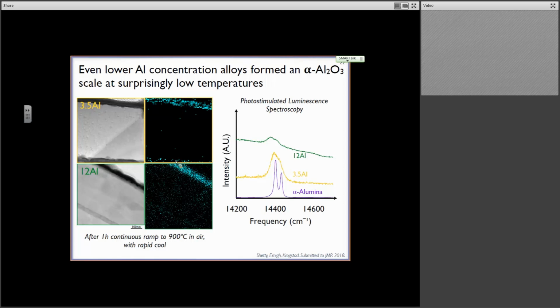You can see that, sorry, I didn't put this on here, but the blue is the aluminum in our EDS maps, and so we have in fact formed an alumina scale rather than a chromia scale. If I were to show you the full EDS map, there is no chromia scale. It is just an alumina scale. The chromium metal stays in the alloy, and that's what we would expect.